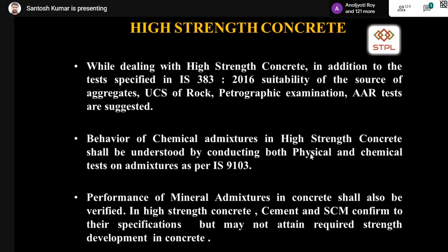And when it comes to high strength concrete, while dealing with high strength concrete, in addition to the tests specified in IS 383, suitability of source of aggregates has to be verified and unconfined compressive strength of rock should be measured. Why? Because for some sources of aggregates, the unconfined compressive strength of the rock may be below 60 sometimes. Even though it is granite, the unconfined compressive strength of the rock may be below 60. And if you use those kinds of aggregates in high strength concretes, the aggregates may get crushed. So UCS of rock is more important.